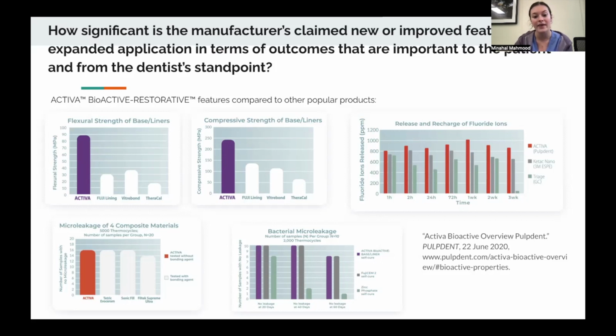Composites are strong, highly aesthetic filled resins, but due to poor adaptation to tooth structure, they have a high failure rate and last an average of 5.7 years. Glass ionomers are bioactive but have a low strength and poor aesthetics. Resin-modified glass ionomers have lower sensitivity to environmental moisture changes, but their aesthetics and physical properties do not compare to other composites. Activa Bioactive Restorative is strong, looks good aesthetically, and is bioactive.